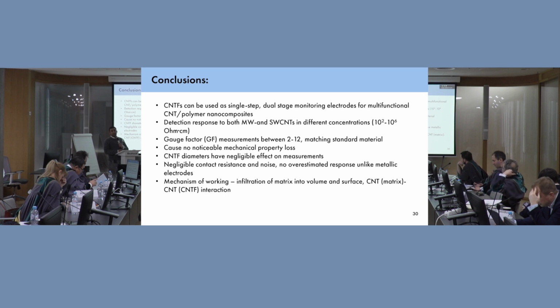And so far, we did not see for our tensile properties any loss in mechanical properties. Our diameters really didn't seem to have an effect on this either. And our contact resistance was eliminated during both stages because of the enhanced interaction, infiltration of the matrix into the volume and the surface, and good connections in this case.